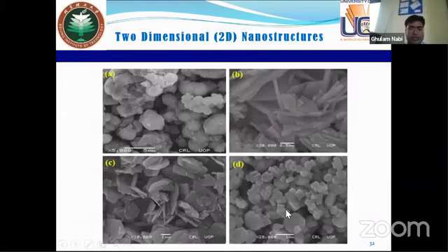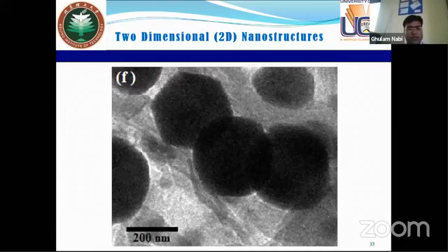and here you can see the nanosheets in diagrams A, B, and C. The nanosheets are not very clear, and if we increase the concentration of vanadium, then we can get purely hexagonal nanosheets, which are being used for supercapacitor electrode applications. Here is the TEM image for the confirmation that the hexagonal nanosheets have been prepared accurately.